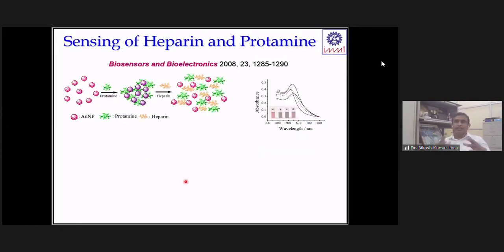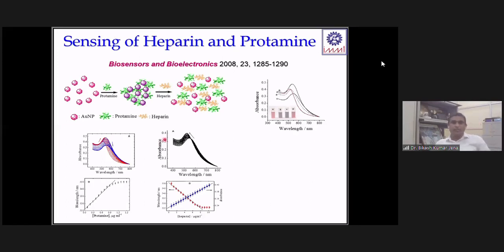So here, we tried to develop an optical sensing system. We synthesized the negatively charged, citrate stabilized gold nanoparticle. When you add protamine, which is a highly positively charged molecule, it will interact with the nanoparticle and aggregate it. The interparticle distance of the nanoparticles decreases, and the color changes to blue. But when you add heparin, there is a strong specific interaction between heparin and protamine. Then protamine will release the nanoparticle, and the original color will come back. With this aggregation, de-aggregation, assembly and disassembly, we were able to monitor the concentration of protamine and heparin. You can see when you add protamine, how the absorbance is slowly decreasing and the wavelength is shifting.